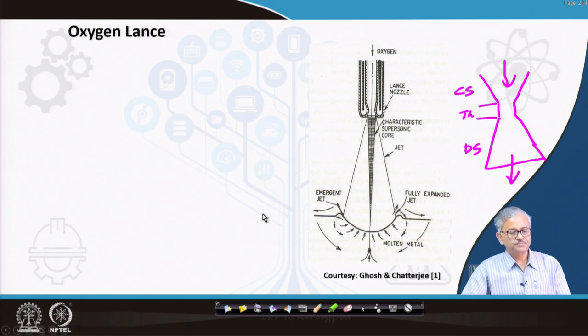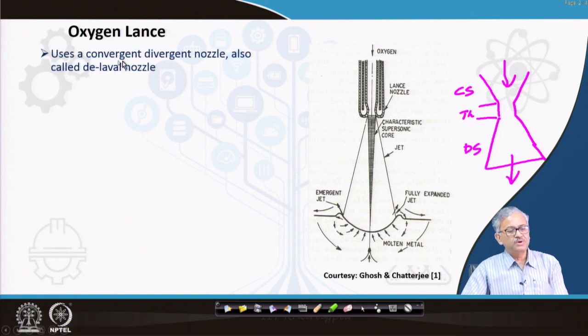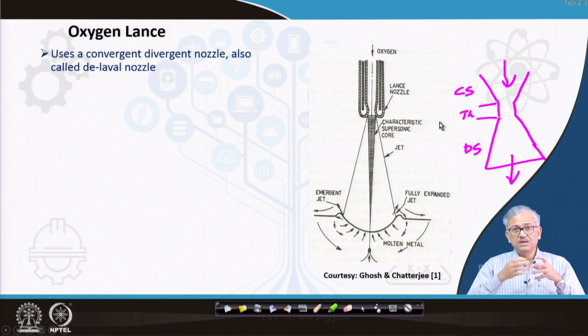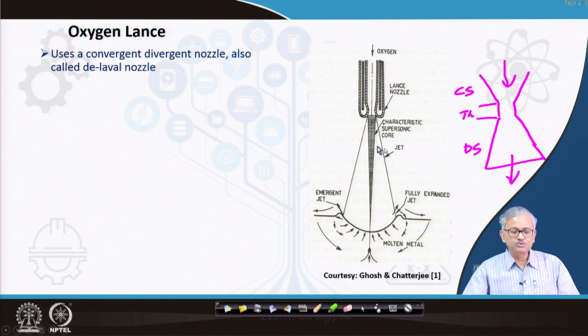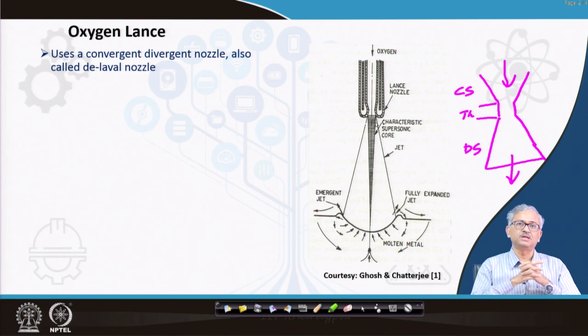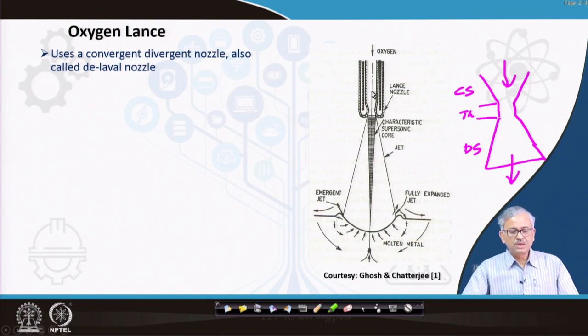Okay. So it uses a convergent divergent nozzle, also called the De Laval nozzle, instead of a cylindrical nozzle, because you can see here a supersonic jet is forming. Basically by a convergent divergent nozzle we can accelerate the gas to a supersonic speed, that is, a speed greater than the speed of sound, right? So that is called supersonic speed. We can push the oxygen at a very high velocity from this nozzle.